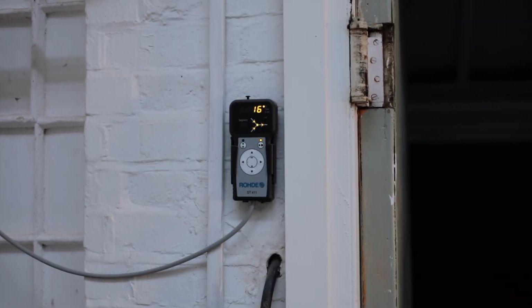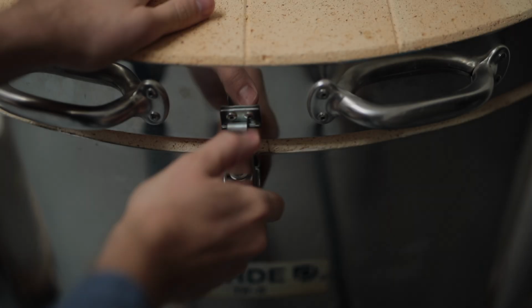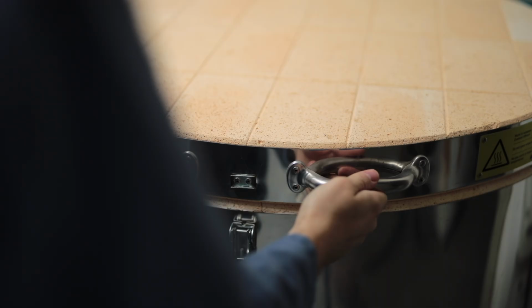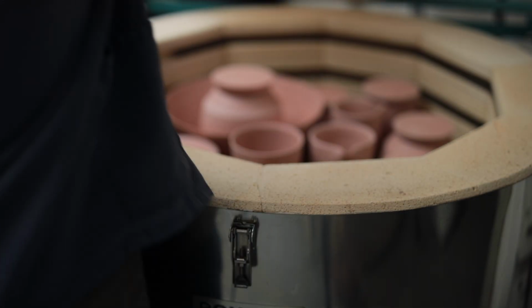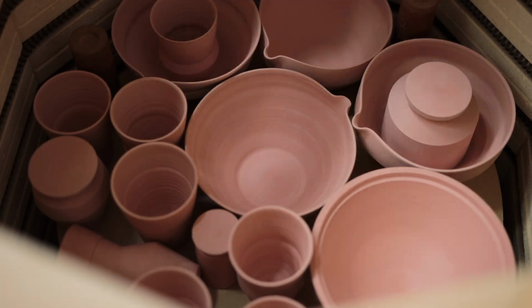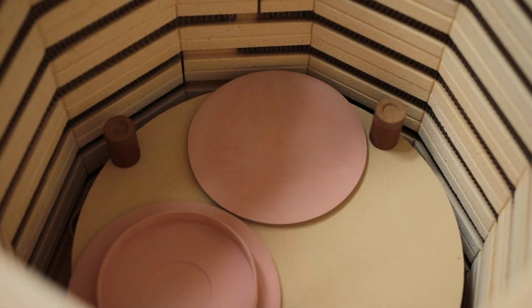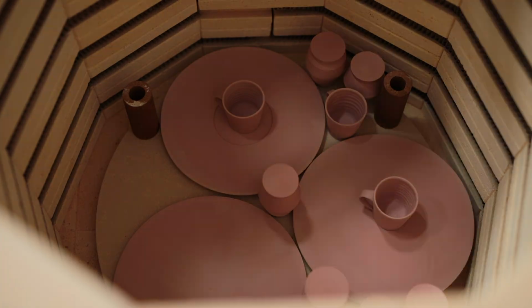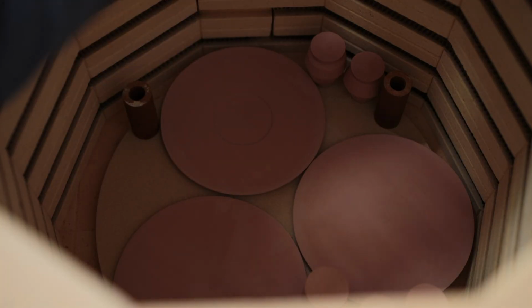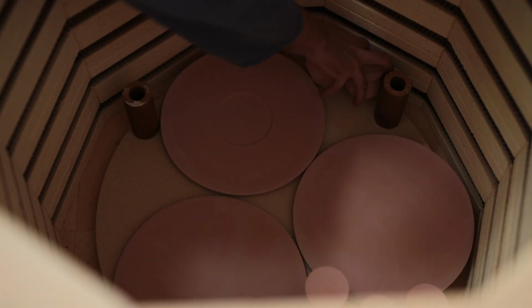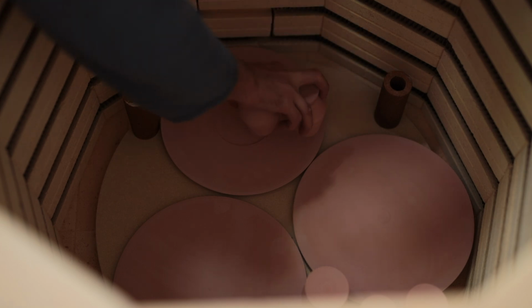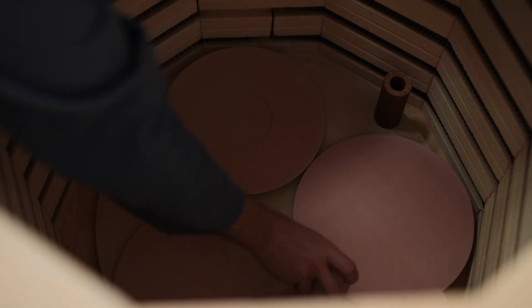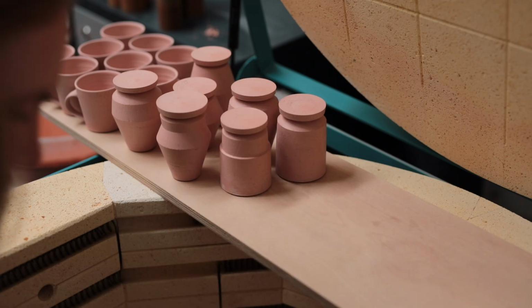These electric kilns can be fired automatically overnight, and a few days later, once it's cooled down from 1000 degrees back to ambient room temperature, the kiln can be unpacked. The pots have once again lightened in colour, and they've also shrunk a tiny bit, as this stoneware, from when it's freshly thrown to finally glaze fired, which will be the firing after this, will shrink about 12%, which means my miniature jars will get even smaller after being fired to 1290 degrees.